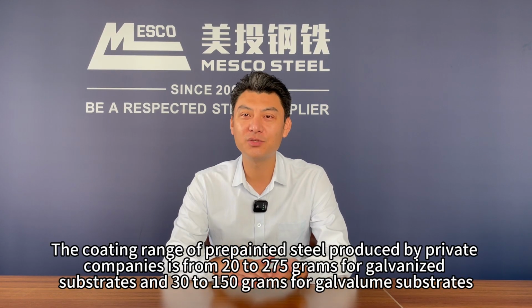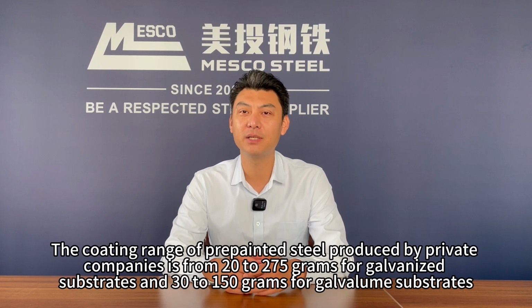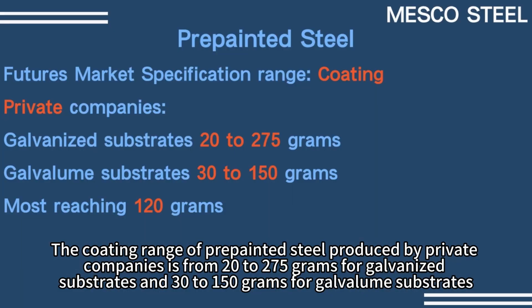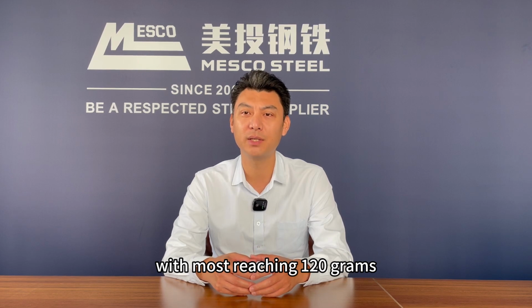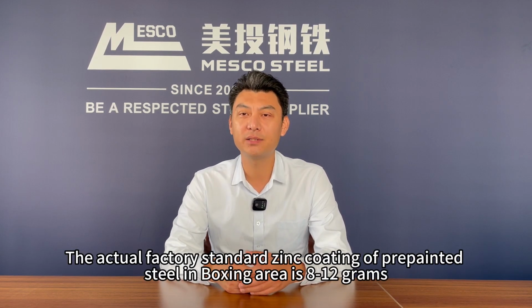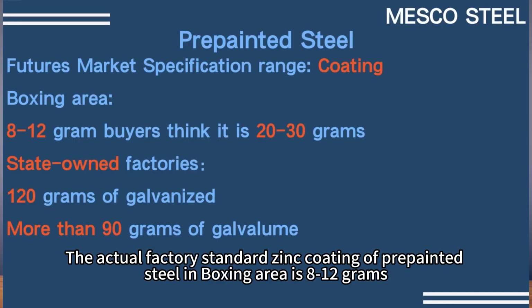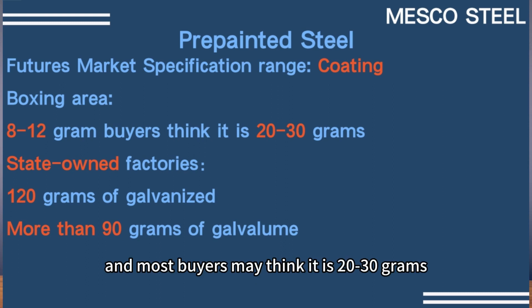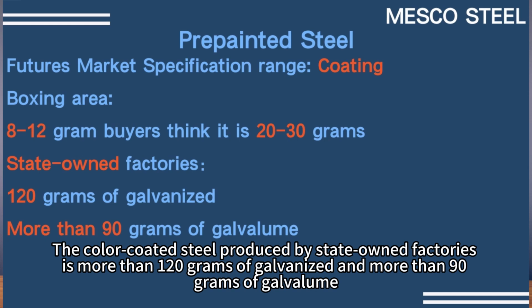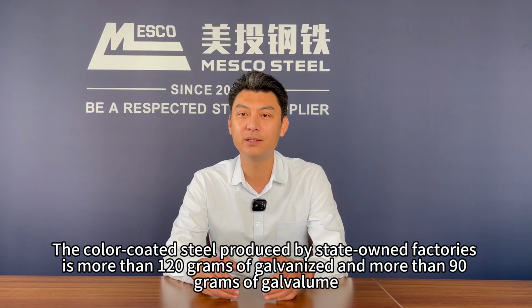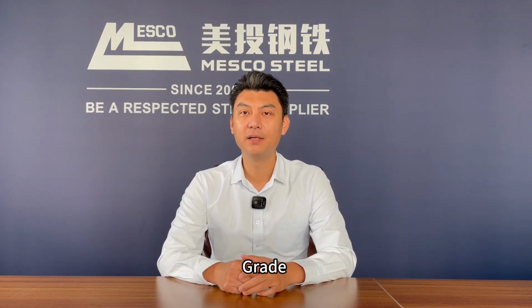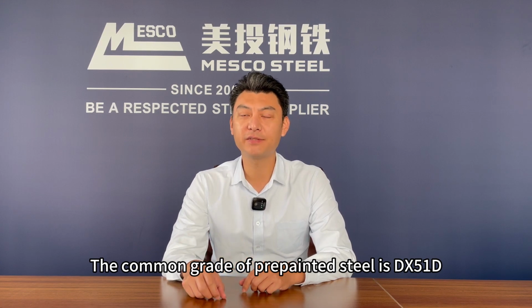Coating. The coating range of prepainted steel produced by private companies is from 20 to 275 grams for galvanized substrates and 30 to 150 grams for galvalume substrates, with most reaching 120 grams. The actual factory standard zinc coating of prepainted steel Boxing area is only 8 to 12 grams, and most buyers may think it is 20 to 30 grams. The color-coated steel produced by state-owned factories is more than 120 grams of galvanized and more than 90 grams of galvalume.